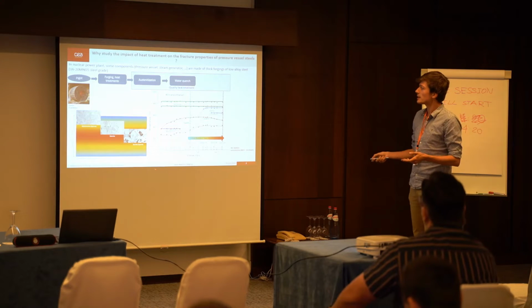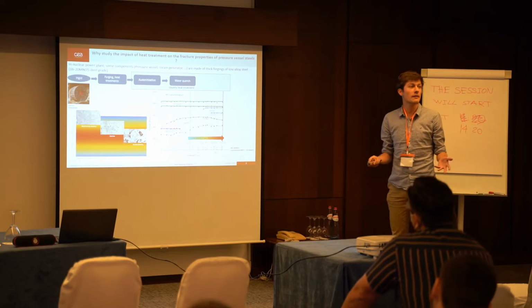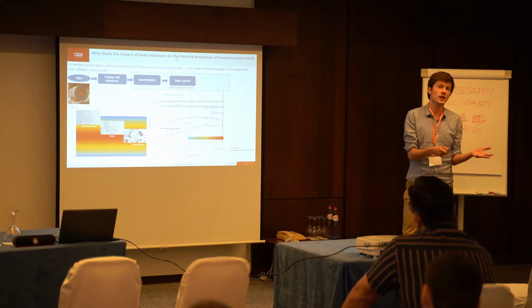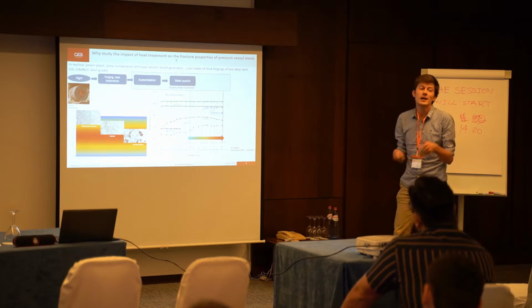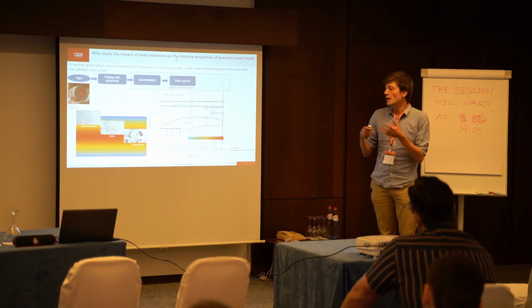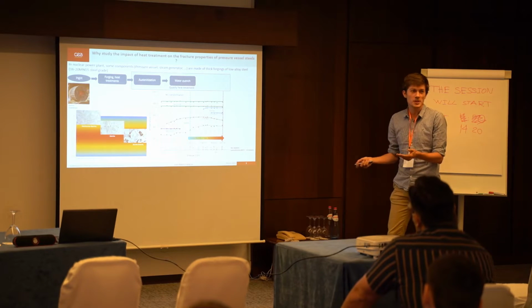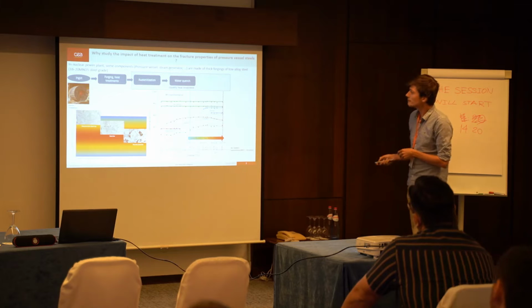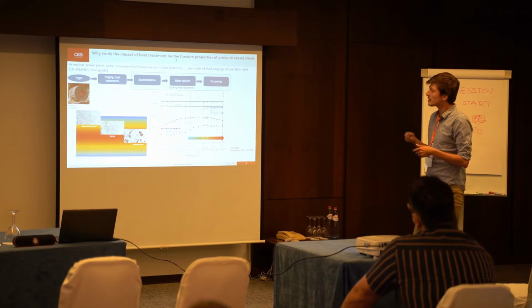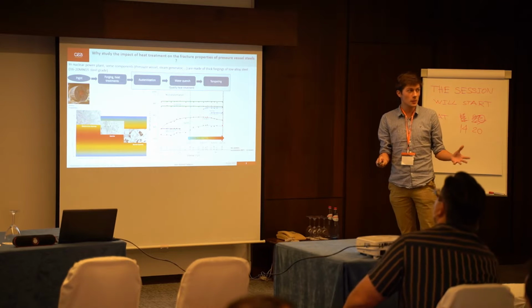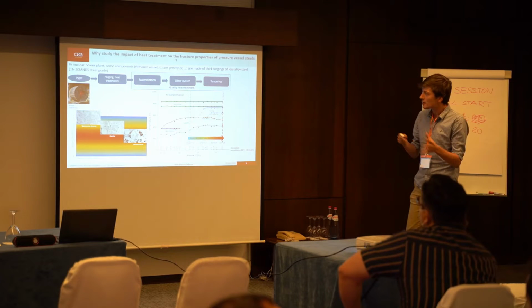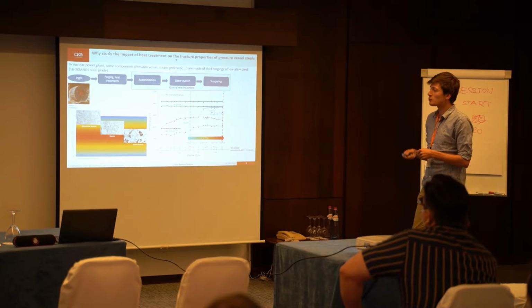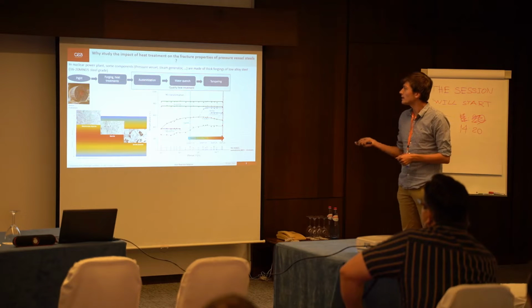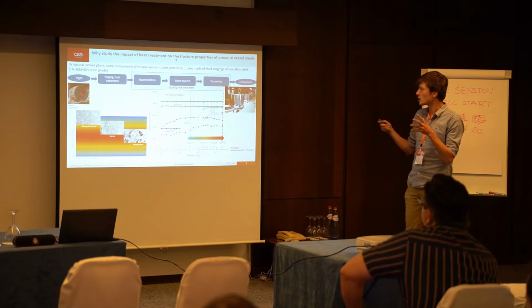However, the cooling rate impacts the microstructure that you have. So you have a gradient of microstructure through the thickness, and as a consequence, you have a gradient of mechanical properties through the thickness. Following the water quench, there is a tempering step to try to homogenize some of the mechanical properties. And we will see that you cannot homogenize every mechanical property of the components. And then, after some milling steps, we have a component that is ready to be assembled in a nuclear power plant.